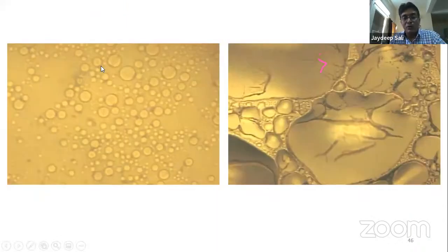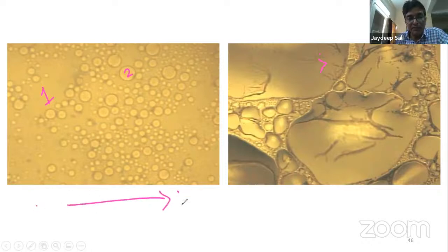Okay, so as I have told you, this is a photograph of a microemulsion. You can see this is one phase, and say this is the second phase. If you create a thin film of such a microemulsion on the substrate, as time passes, the state of the microemulsion goes on changing. The microemulsion may become stable, it may become unstable. If it goes towards instability, these two drops may merge with each other and form a big drop.